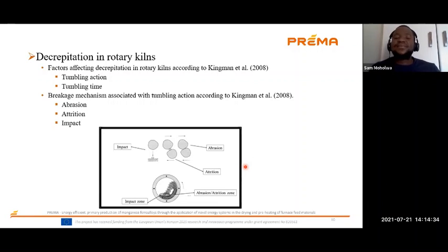Decrepitation in a rotary kiln is mainly affected by two factors. We have the tumbling action, which is the movement of the particles in the kiln, and you have the tumble time. But in this case, since the residence time has been kept constant, we'll only be focusing on the tumbling action that happens inside the kiln. This tumbling action can be further divided into three mechanisms. We have abrasion, which is a process where two particles of the same size rub against each other when the kiln is moving. This friction caused by them rubbing against each other may produce fines. Then we have attrition, whereby we have two big particles rubbing against a small one to produce fines.